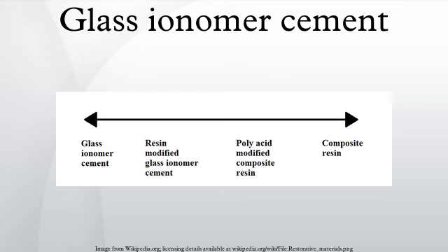Although they reported no significant difference in overall failure rates after 2 years, follow-up of the restorations up to 5 years showed that glass ionomer restorations had significantly inferior survival time to amalgam. The importance of long-term clinical studies should therefore not be overlooked. Other short-term trials also show poor success rates of conventional glass ionomer restorations in primary molars.